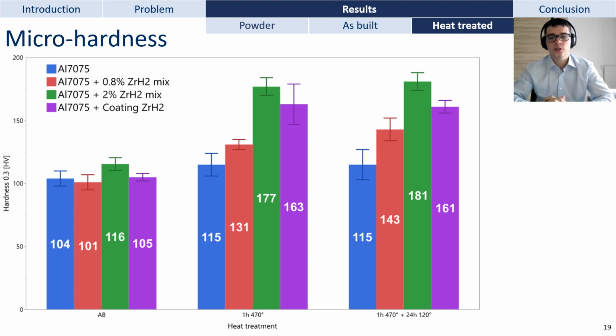The last thing to mention is that these values of microhardness are obtained for samples that have lost a lot of zinc and magnesium during the process, so they are supposed to have fewer alloying elements to form hardening precipitates.